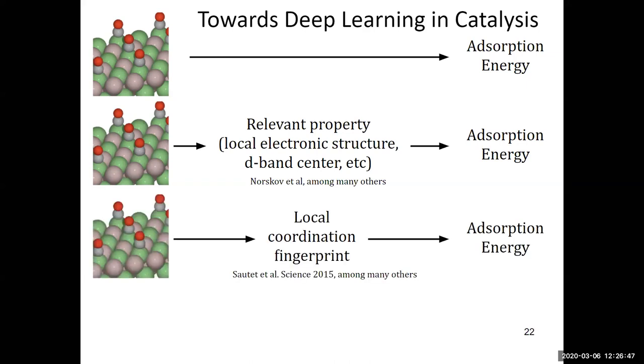So other people obviously recognized that this is a problem. And there was a great sequence of papers developing coordination-based approaches and things like the generalized coordination number to explain how the activity changes as a function of how under-coordinated the surface atoms were. This works awesome if you have a single metal. So if you're just dealing with platinum and you're trying to figure out what is the activity of a structured platinum interface, these things work great. Nobody really has a model that works across different elements in the same way. I don't know what the equivalent of a coordination number for a bimetallic is, where two different components have different numbers of neighbors. Right? That's a hard problem.